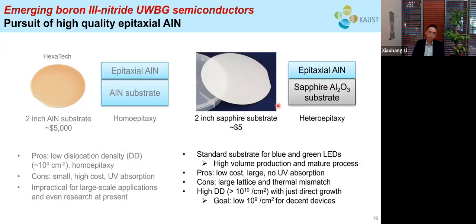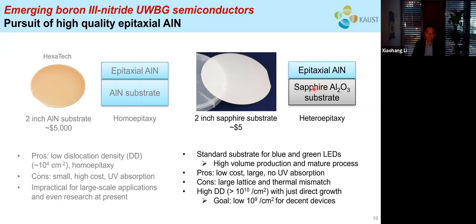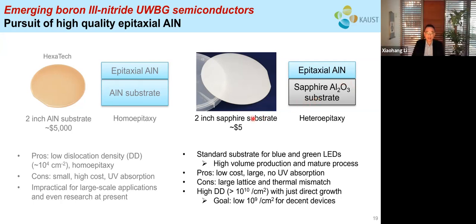Another kind of substrate is the sapphire substrate. Sapphire is basically aluminum oxide. In comparison to the aluminum nitride substrate, the sapphire substrate is very, very economical. A 2-inch sapphire substrate costs merely $5. This is thanks to the high volume production of sapphire for blue and green LEDs.